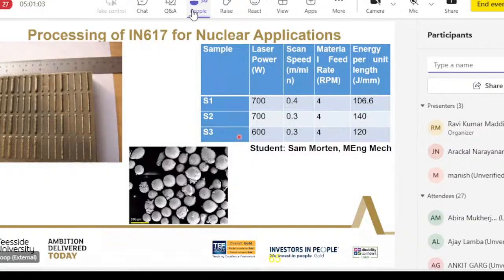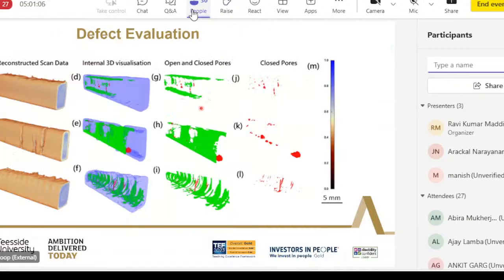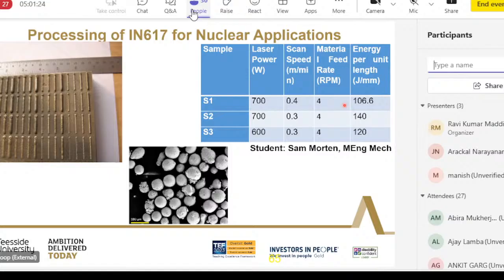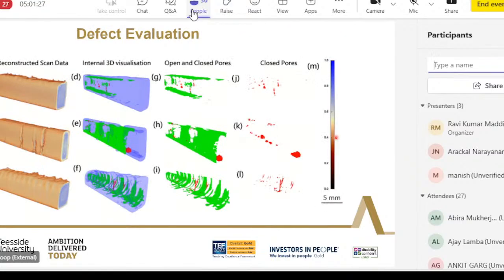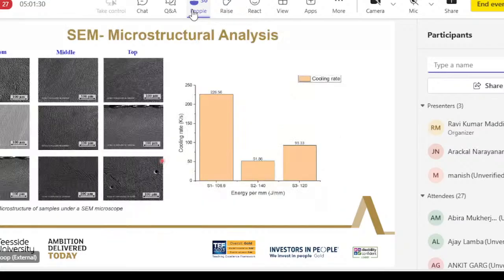Within that, we could see that the high energy density samples have got a lot of cracks in them. A lot of defect formation was seen on these samples. If you see the S2 sample, it has got a higher intensity of closed pores as compared to the other ones. S2 has got higher intensity than S3 and S1, which again is showing a clear correlation between energy density and the defect formation that is generated in the samples. Regarding the variation in the grain structure, the higher energy density samples have got a coarser grain structure, and as we move towards a lower energy density, we are getting a finer grain structure.